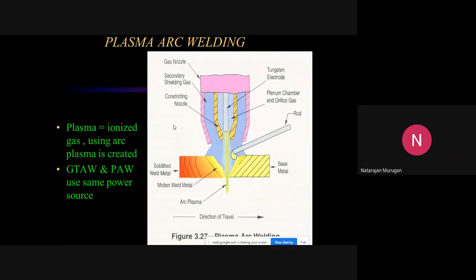Okay, but in plasma, practically we use 17,000 to 18,000 degrees centigrade. The idea is that you pass another gas, called plasma gas or center gas or orifice gas, which comes through the orifice and passes through the center; that's why it is called center gas. When it comes out as a plasma, very high heat is produced. The energy level goes up to 10 power 7, 10 power 8 watt per meter square. Okay, 10 power 8, it goes up to that.